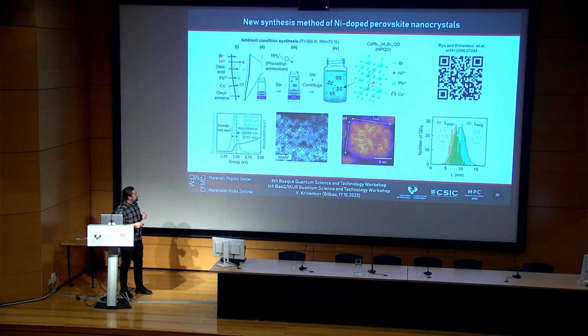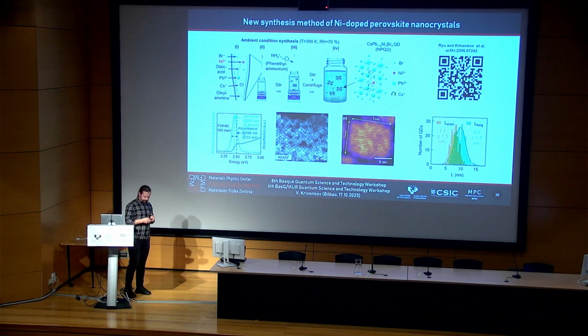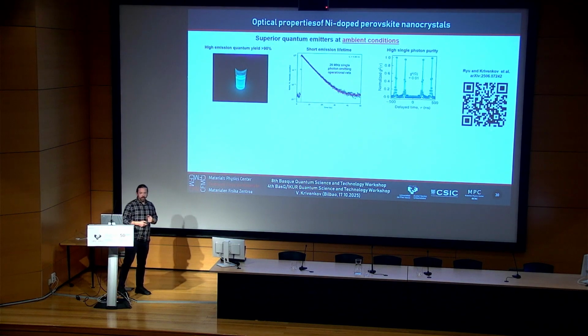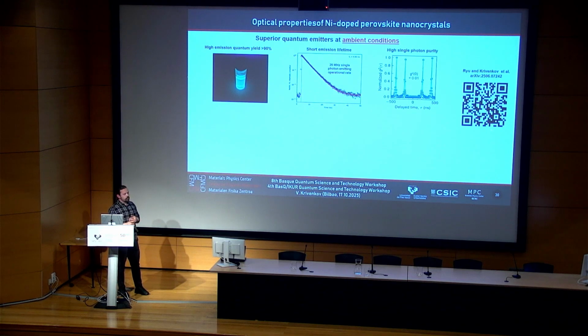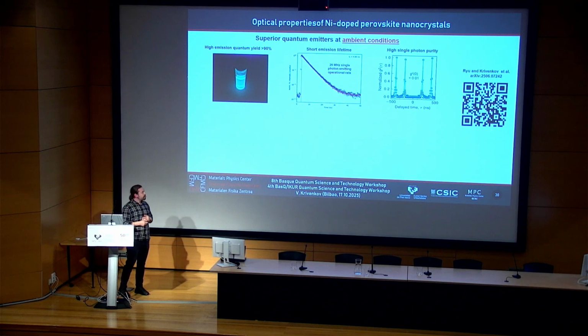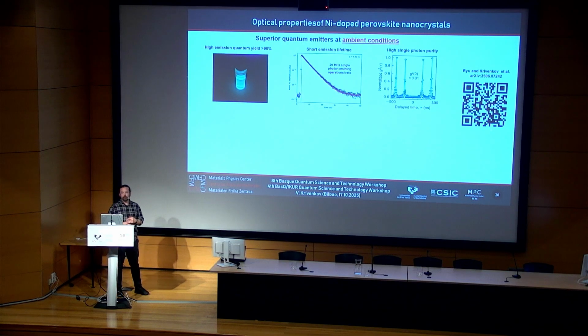And not only could we achieve high crystal quality, but we also achieved very good optical properties of these nanocrystals at the level of single particles. We implemented doping of our nanocrystals with nickel, and it allowed us to achieve a high photoemissive quantum yield of more than 90%, for some samples almost 100%. Short emission lifetime of about 5 nanoseconds, and most importantly, a very high single photon purity level of about 1%, and for some samples even lower, at room temperature.